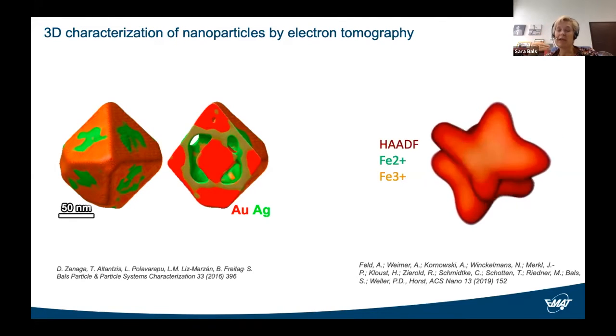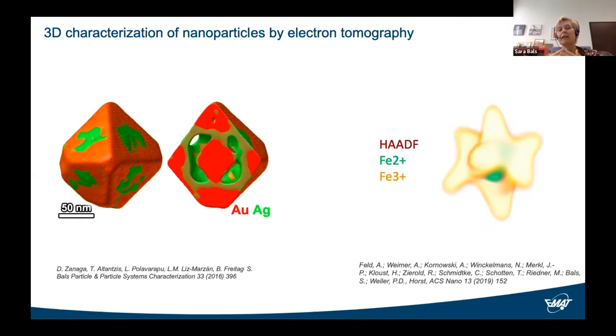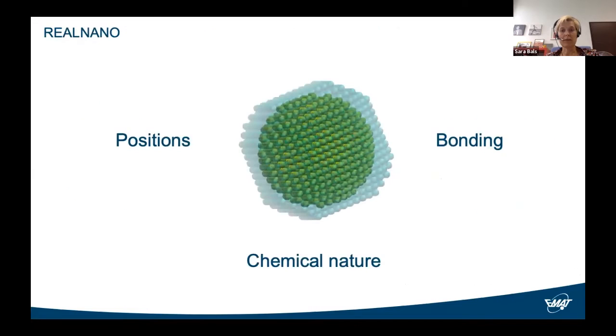And if we compare this with reference spectra, we can determine the valence in 3 dimensions, and we could reveal in this specific case a core shell structure which is related with the exact type of iron oxide phase present in this nanostar. So these examples have demonstrated that indeed we are able to determine the positions of the atoms in a nanoparticle, and that we can also measure chemical nature and bonding in 3 dimensions.